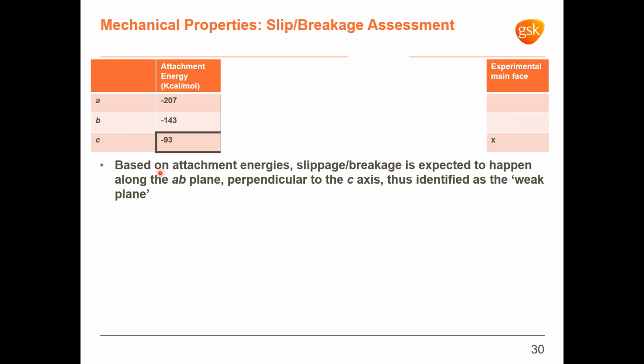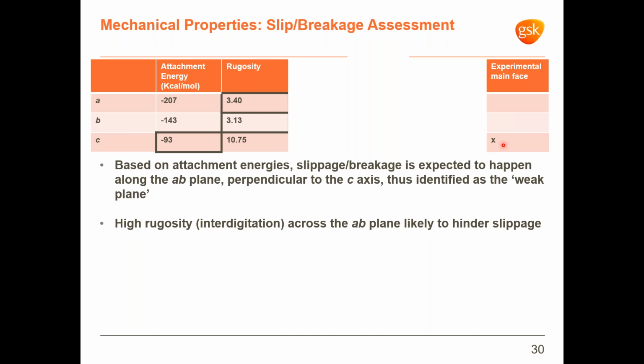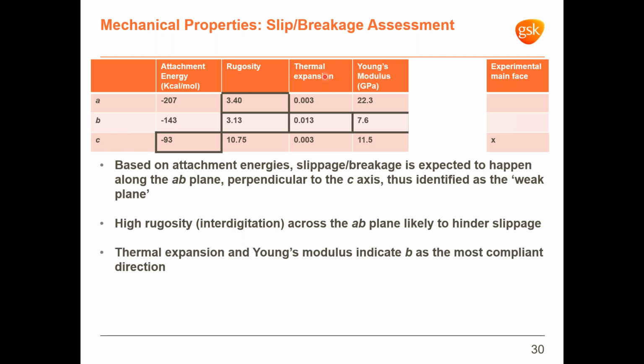So trying to summarize all the most significant gathered indicators along with calculated elastic properties in a comprehensive assessment, we have the attachment energies based on which slippage breakage is expected to happen along the AB crystallographic plane. And in accordance to this, it is also predicted to be the experimental main face. Rugosity, based on which slippage along the AB plane, on the other hand, appears prevented in relation to the high degree of interdigitation occurring across the planes. And Young's modulus and thermal expansion calculated values, both suggesting the B direction as the most compliant one.